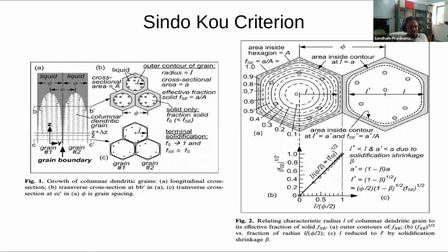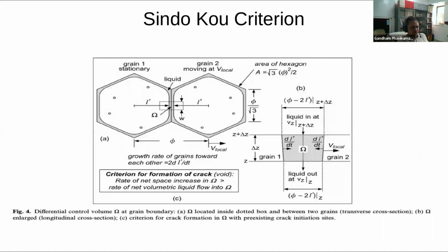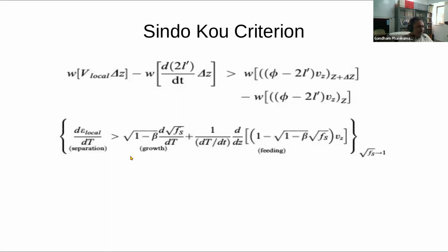We have addressed some of it in our studies recently to avoid the limitations of Kou's criterion, which is only a grading of alloys for cracking, but we can also predict the crack-free processing regimes using this. So here is the equation. Here you can see the rate at which the strain is changing with respect to the temperature must be larger than certain terms: one of them is how the liquid fraction or solid fraction is changing with temperature, and the second term has a cooling rate. This equation has to be evaluated in the limiting condition towards the end of solidification.